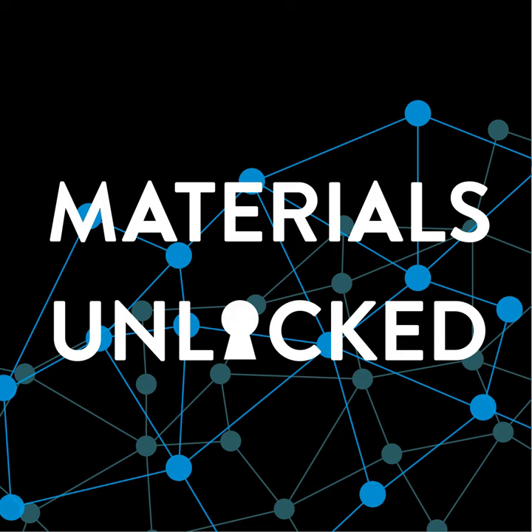Those have huge implications, because materials that look great from a starting point, if we take them as received and test them, give lovely material properties: excellent strength, excellent toughness, all the sorts of things we're looking for. But what happens when we start to neutron irradiate them is they change dramatically. In some cases, it's not even like you're looking at the same material anymore. Normally we see effects such as hardening with irradiation, so the materials become very brittle. They no longer have the same elongation you had in the as-received state, so they lose a lot of their plasticity. You don't have any ability for the material to deform before failure, which is a huge concern for us.